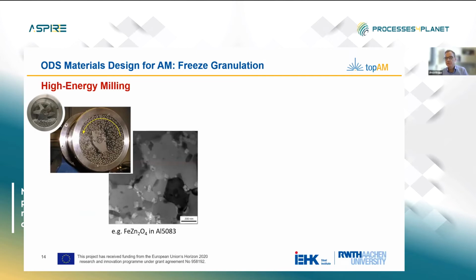particles in the material. One is a high energy milling of the ceramic material in combination with a metallic powder. That shows one example where we have done this with an aluminum alloy here. So you see those small grains and then the nano-sized particles.